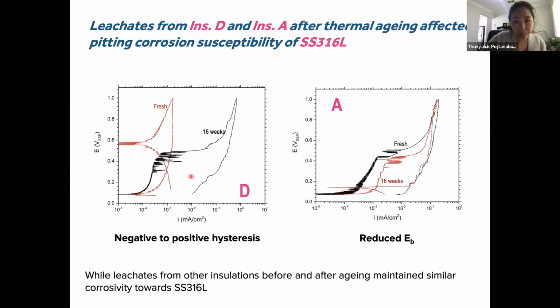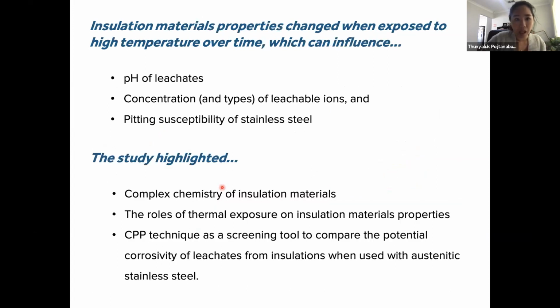But we repeated the same test with thermally aged insulation, and what we see is a significant drop in the breakdown potential, showing that over time, after aging to a certain degree, the insulation can change and it provides different risk to the substrate. So this is a highlight of the insulation part of the presentation, to show that the high temperature exposure affects the pH of the solution. It affects the concentration and the types of leachable ions. It also affects the pitting susceptibility of stainless steel.